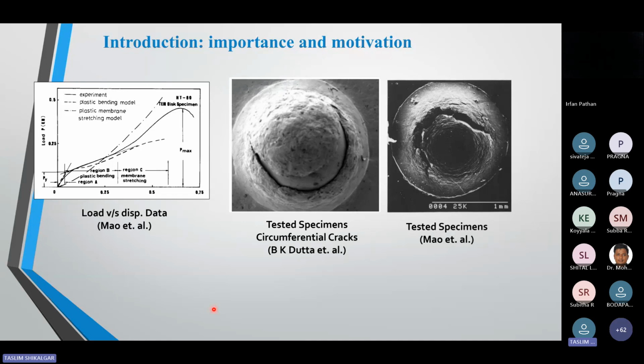This is just more introduction about the SPT. I took 3 images from the literature. After testing the SPT specimens, you get this load versus displacement data. This is not equivalent to the load displacement data we get from the tensile specimen. So how can we get mechanical properties with the help of these specimens? Much research has been done. One point here is known as the yield load, and the second point here is known as the ultimate load.